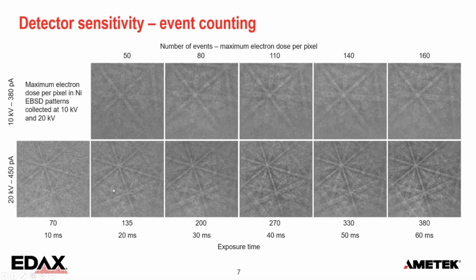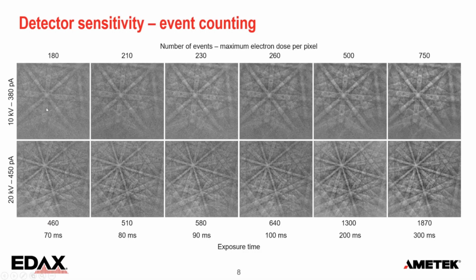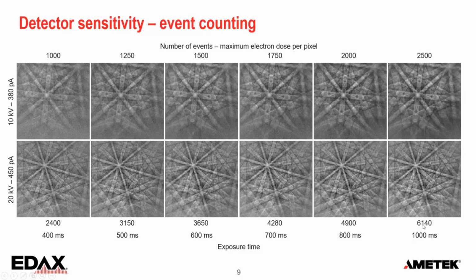At 20 kV, we get a larger signal in the material, but also in the detector. It's more sensitive. It just gives a higher electron hole pair result for each impact. And you can see we get more electrons coming in. We can also measure a little bit shorter. And also here you can see the contrast increasing. So if we just go up, you see the details are already here at a few hundred electrons. But if we keep going, we get more and more detail. And here at 2,500 to 6,000 electrons per pixel, you have really nice diffraction patterns with lots of detail, very sharp edges.